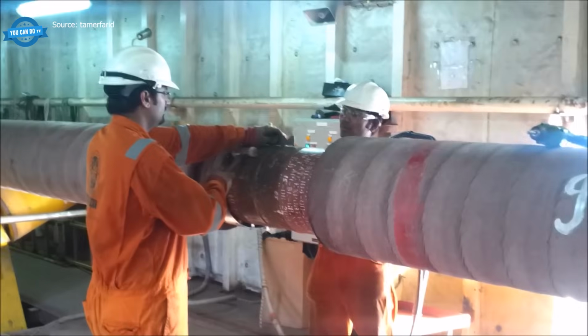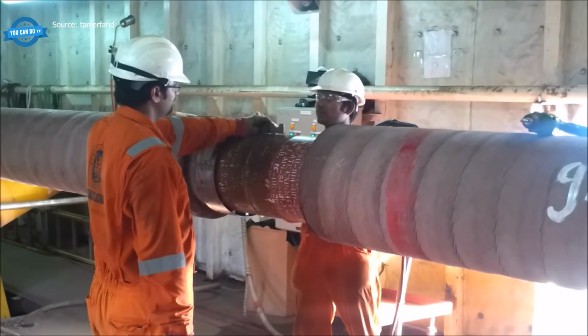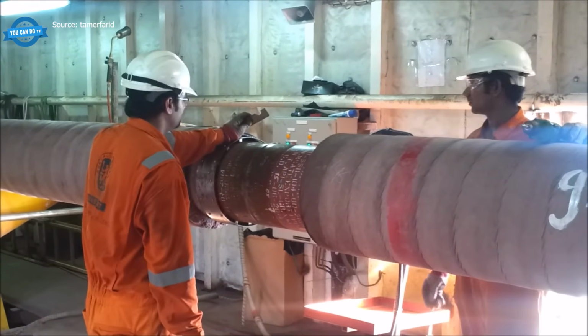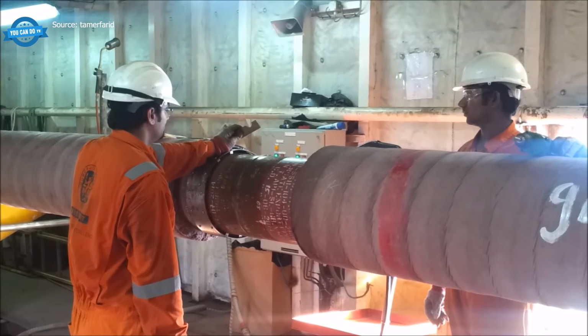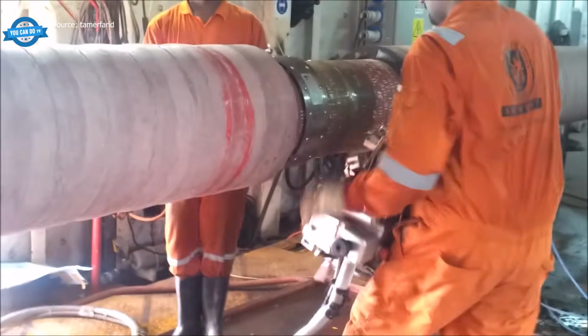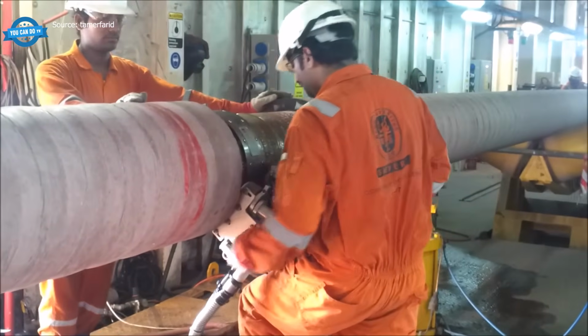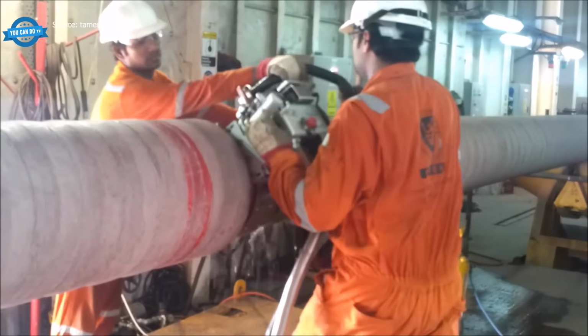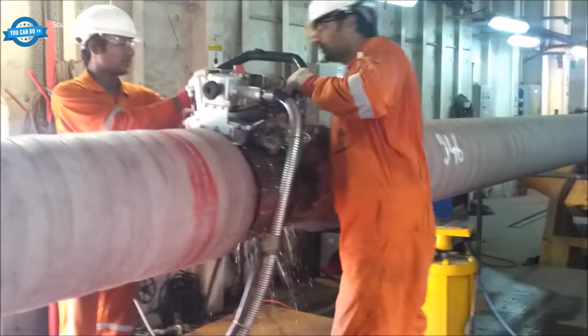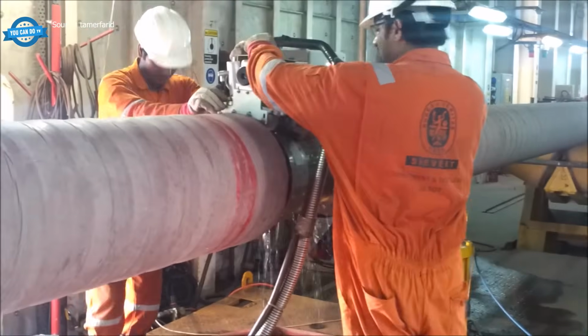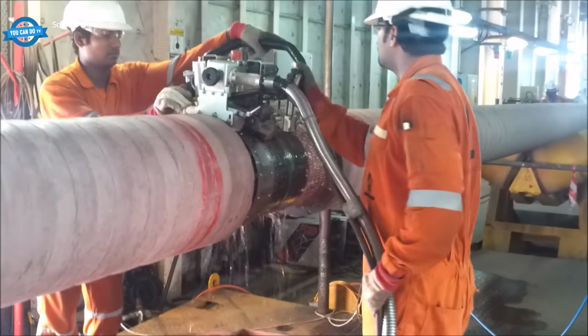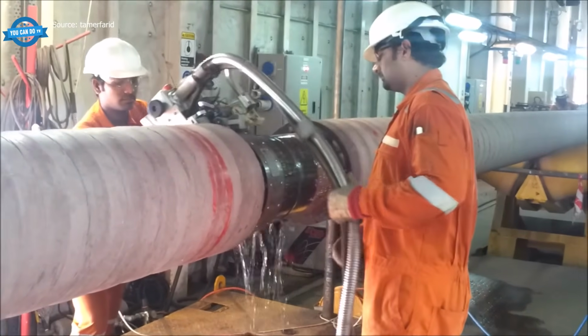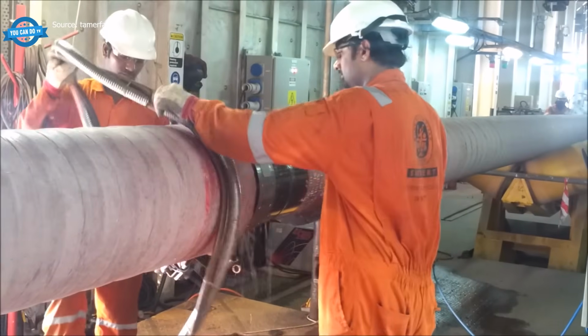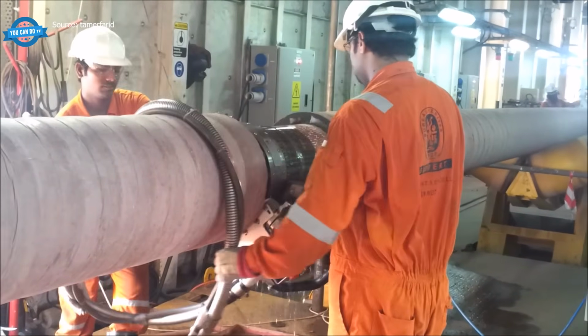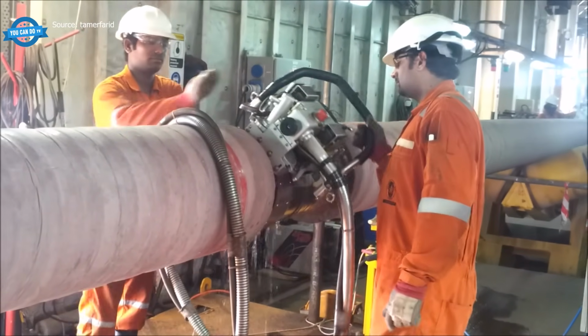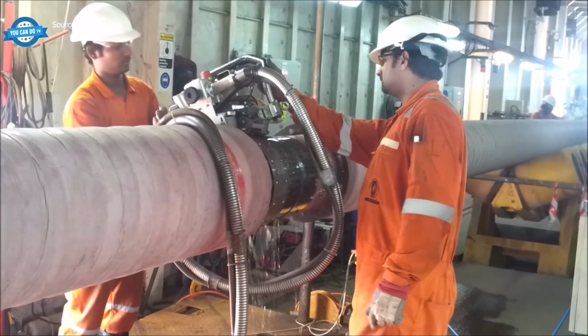A corrosion-resistant heat-shrink sleeve is centered over the joint and heated until it tightens against the steel. Polyurethane foam is then injected into a closed mold around the sleeve and allowed to cure, restoring the full coating cross-section and mechanical strength of the original factory coating. Every step is timed against the lay rate of the vessel. A delayed or defective field joint coating slows the entire pipelay operation, and an undetected one becomes a long-term failure no one will find for years.